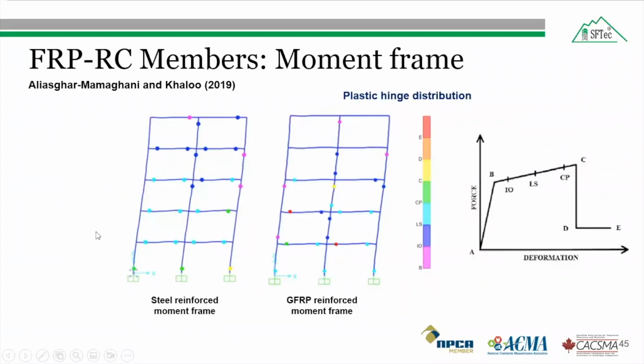The hinging pattern of the steel reinforced moment frame, which can be shown here, showed a desired beam sideway mechanism. So in other words, it showed a strong column, weak beam mechanism. Whereas the hinging pattern of the frame reinforced with GFRP bars conformed to a weak column and strong beam condition, leading to a formation of plastic hinge in the columns of the middle story, as you can see here, which resulted in a column sideway mechanism due to the failure of the column in the third story.